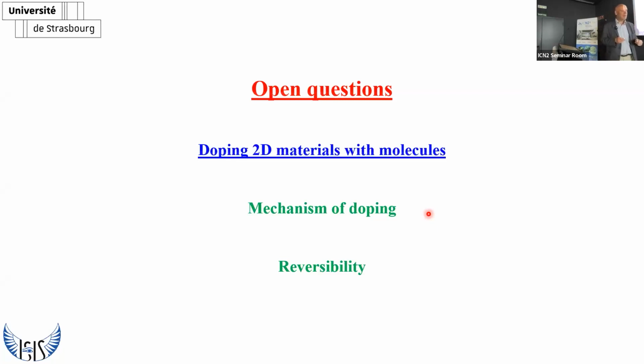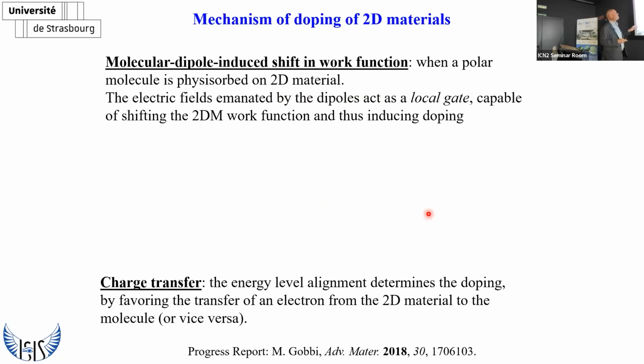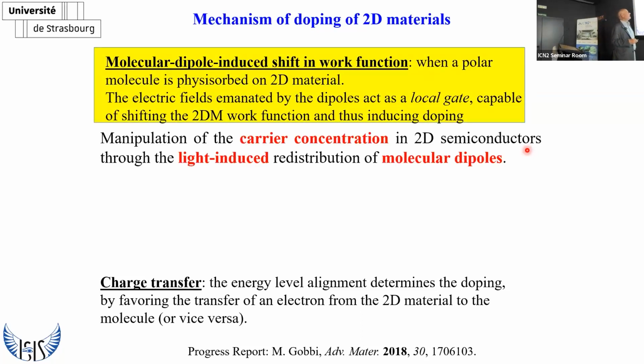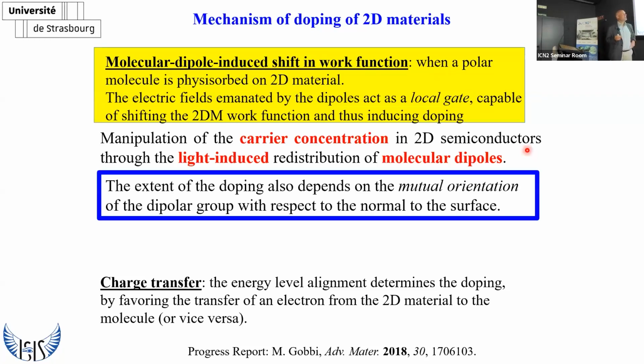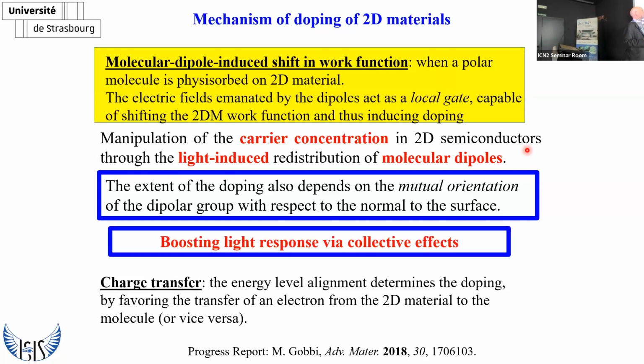Let's look at the mechanism of doping and reversibility. The first thing is there are two different mechanisms by which you can dope the materials with molecules. One is what you can achieve by using molecules that have a high dipole moment, and if you deposit them on the basal plane of the materials, this would be the electric field that is emanated by the dipole that would behave as a local gate, would shift the work function of the materials and induce the doping effect. And so, at this point, playing with dipoles, the more dipoles you have all oriented in the same direction, the better it is.